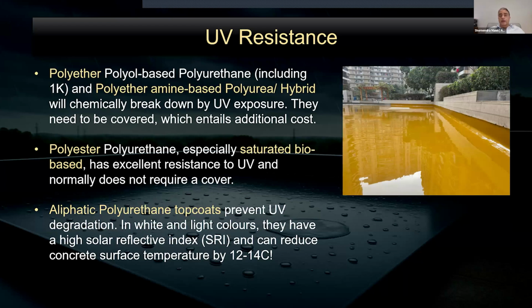prevents UV degradation, but in lighter shades, they have a very high solar reflective index. We have in fact measured that between uncoated and coated surface, the difference in surface temperature in peak summers is as high as 14 centigrade. So you are saving a lot of energy in the whole building. And in fact, we can avoid the heat islands.